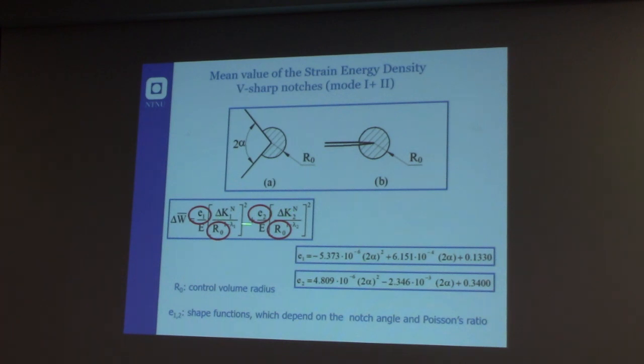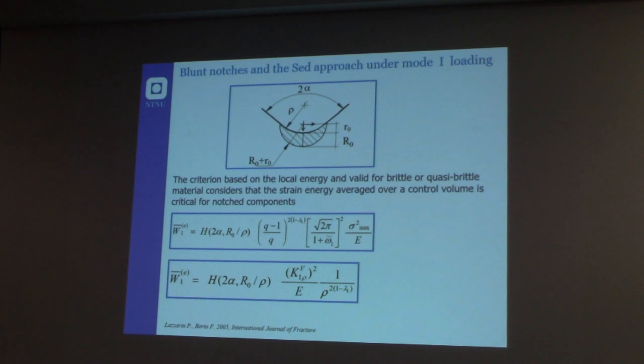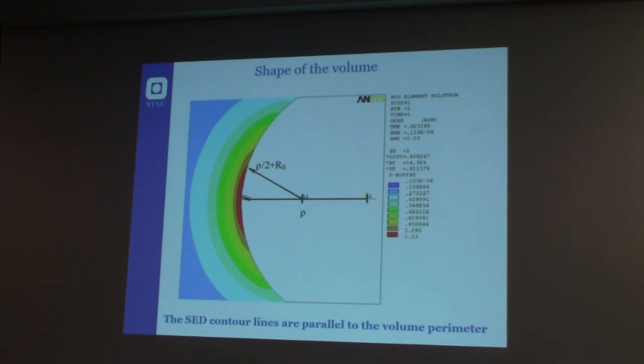And actually delta K1 is there because we are thinking of this equation for fatigue application, so we always use the range of delta K. But E1 and E2 are only a function of the notch opening angle, so it's very easy to evaluate them if you have these simple expressions. So they are only a function of 2 alpha, and this expression can be used with a simple calculator. And after that we extended the same consideration to a blunt notch, not only a sharp notch. And if you consider a finite element, you can see that the shape of the contour lines is very, very similar to the shape of the control volume that we have selected, actually parallel to that. So this means that the model has also some physical reasons to be very good.